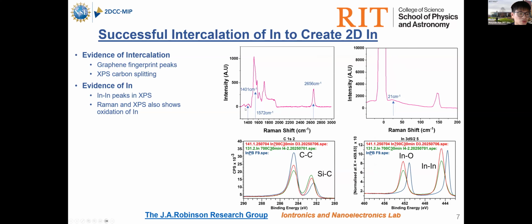So as we intercalate, we do see, sorry for the quality of this Raman data, that's my processing mistake. But anyway, we do see the 2D, G, and D peaks of graphene that give us the decoupling as we intercalate indium atoms, and also we see this carbon splitting from the XPS data. And also for the indium,